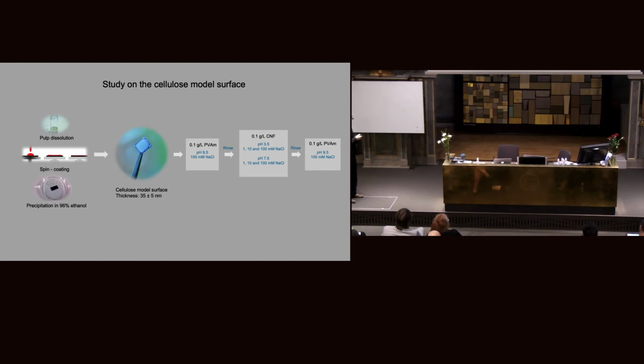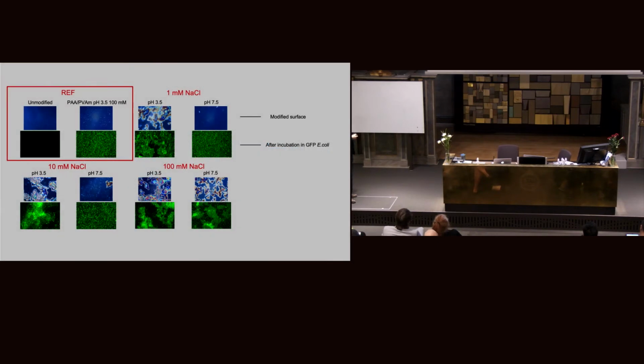Therefore, we create these cellulose model surfaces by spin coating the dissolved pulp onto the silica wafer, and we modify this surface exactly the same way as we modify the fibers. And then we can see the difference between those.